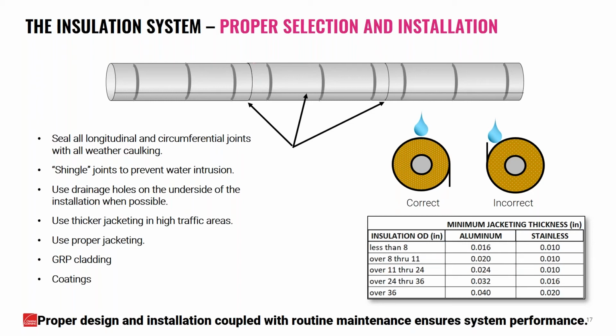Then finally, over in the lower right-hand side, there's aluminum jacketing thickness, and this is created by ASTM. And again, this is a good chart to follow, or recommendations to follow. These should be considered minimums, and of course, there's nothing wrong with going thicker in high traffic areas or even double layering. Again, you want to protect the insulation system from damage. The other part of that too is as you step on it, you kink it, you do these other things, and you not only can fracture the insulation underneath, but also create gaps where water can get in.